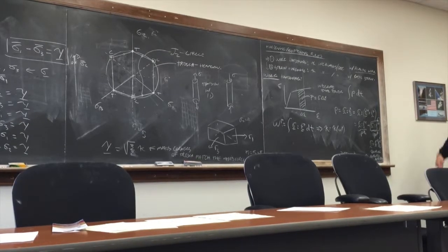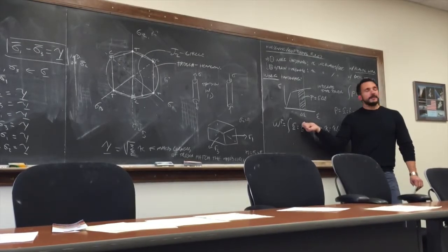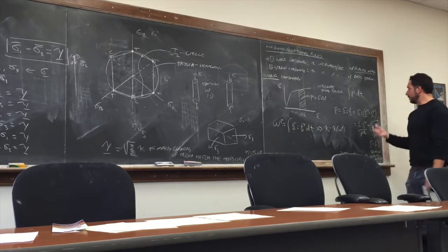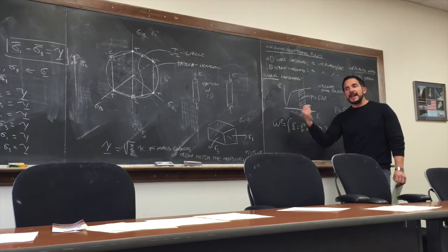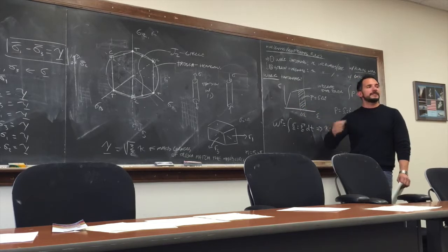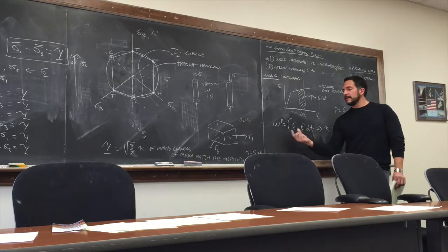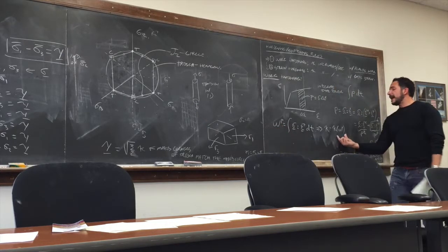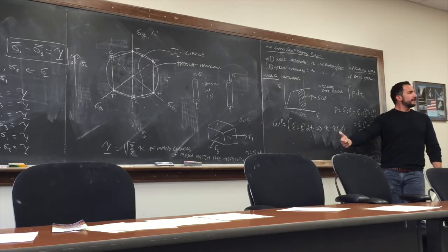So let's just rewind a second. What people do is they compute in the plasticity model the increment of plastic strain. They double contract it with sigma. That gives them the plastic power, or the incremental work, if you want to see it like that. Then you add up as you proceed in the loading process. You keep adding how much incremental plastic work you've done. And what that value is at any time Tn or Tn plus 1, you formulate a function of kappa that essentially evolves with Wp as it evolves.